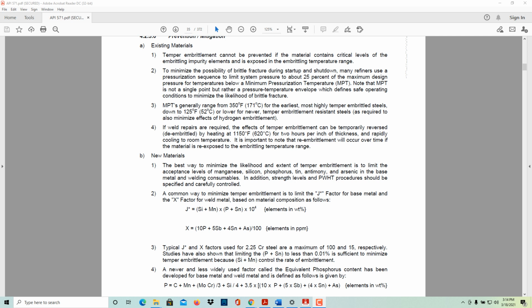New materials. The best way to minimize the likelihood and extent of temper embrittlement is to limit the acceptance levels of manganese, silicon, phosphorus, tin, antimony, and arsenic in the base metal and welding consumables.